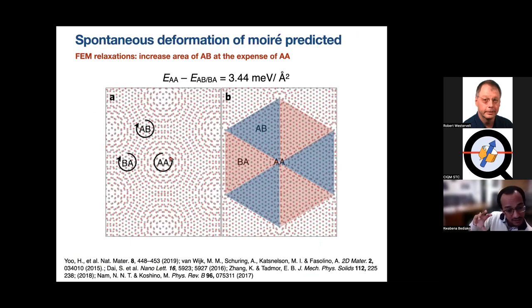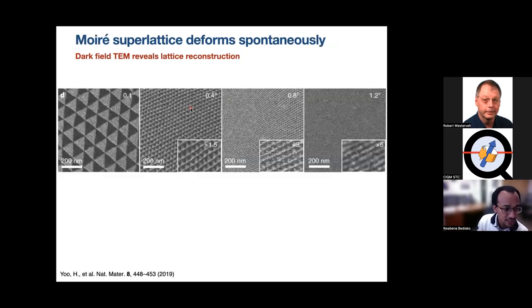showing that there are a series of relaxation processes that involve AB counter rotation against the moiré twist and AA rotation in the direction of the moiré twist that serve to increase the size of the lower energy AB or BA stacking, or, you know, for organic chemists, those are sort of the staggered conformations, and then shrinking the size of the eclipsed conformations of the AA domains. And so what we were really interested in doing is measuring these rotations a little bit quantitatively.